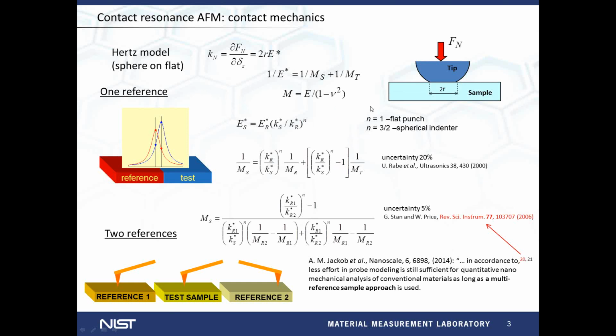But we have a couple of unknowns here, like tip radius. We don't measure directly the contact radius. So a way to bypass some of the unknown parameters, like tip radius, contact radius, cantilever stiffness, and ultimately also to minimize the uncertainties introduced by an appropriate description of the actual contact mechanics, is to perform successive measurements on a reference material and on the test material, take the ratio of the contact stiffnesses that we measure, and determine the indentation modulus of the sample with respect to the indentation modulus of the reference material. Here, a reference material means a material with known elastic modulus, either from calculations or other types of measurements.